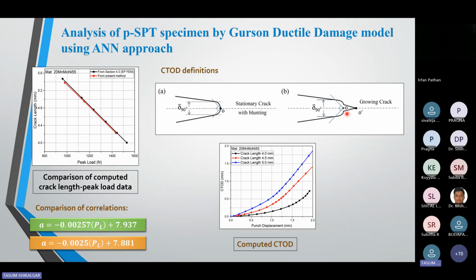If I shift my crack tip from this location to a new location, and you calculate the crack tip opening displacement at the new crack tip, then you will get a lower CTOD value for the next load. You will not get this type of curve. So this methodology is not available for a growing crack.